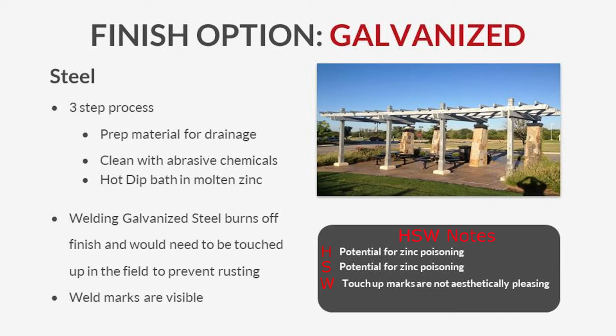The process is labor-intensive as the excessive galvanized spikes or drips must be sanded off of the steel in a uniform layer of protection. The corrosion protection offered by galvanizing is directly linear to the thickness of the coating. The trellis image shown on this slide has a galvanized finish.